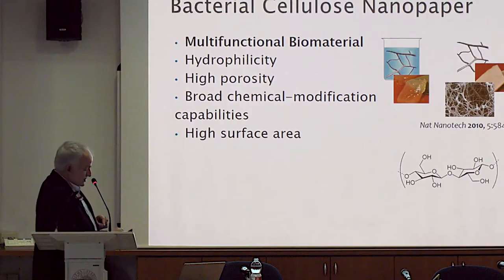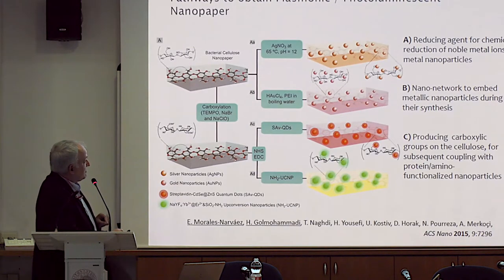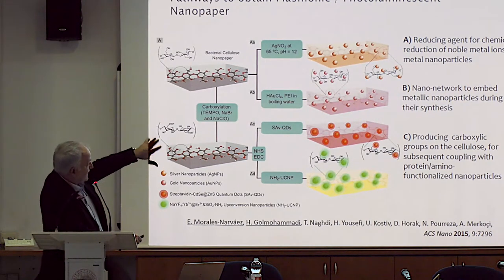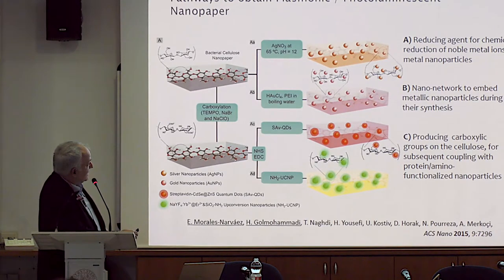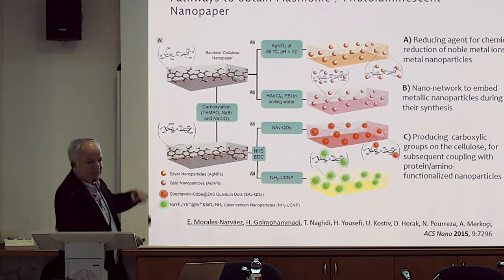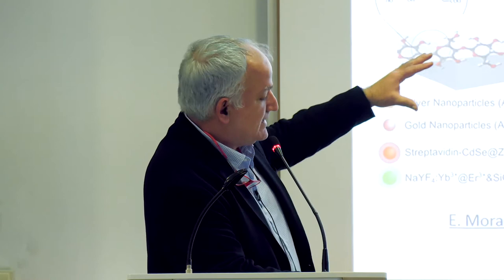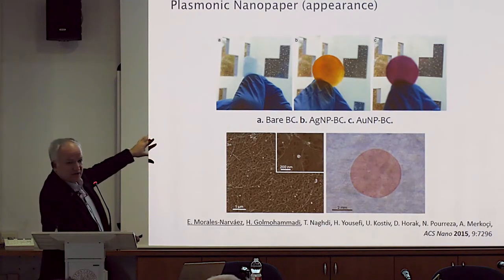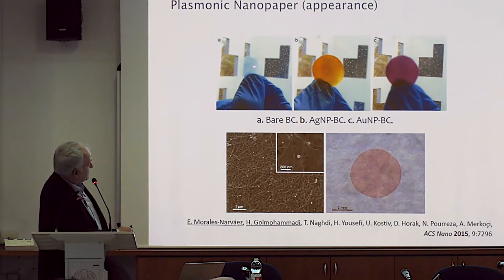Another interesting paper material is nanopaper. This is produced by a special bacteria that is able to produce these tiny fibers, which are really very interesting because this material has a nice capability also to be modified with nanoparticles. So what we do here is the matrix of the bacterial cellulose nanopaper is modified now with silver nanoparticles, gold nanoparticles, or even other up-converting nanoparticles. And we have this piece of paper now with different colors. So you can see here the paper without nanoparticles, the one with silver and gold nanoparticles.